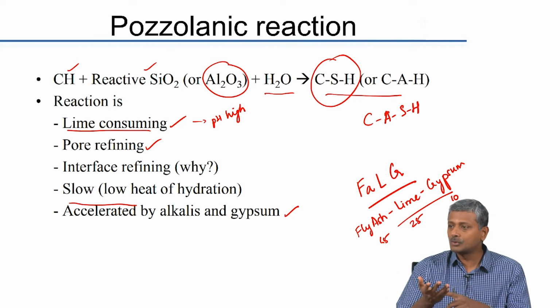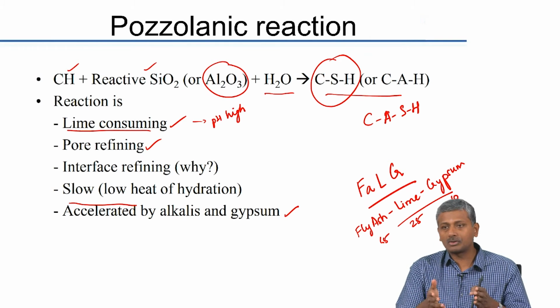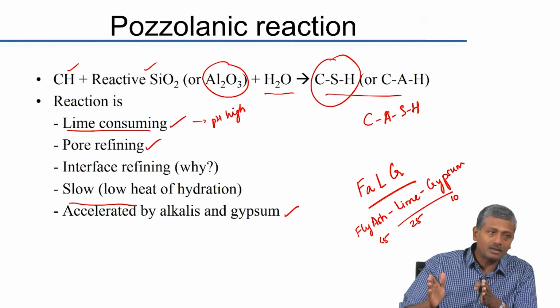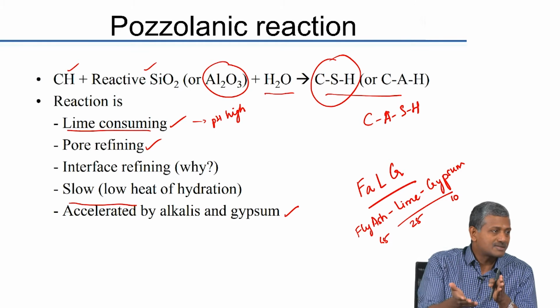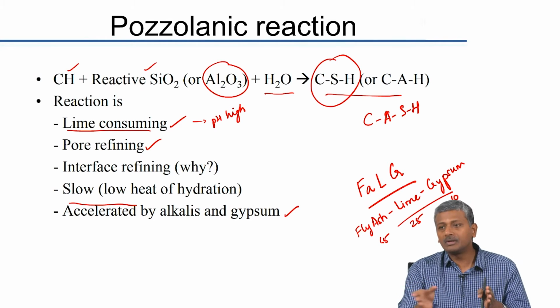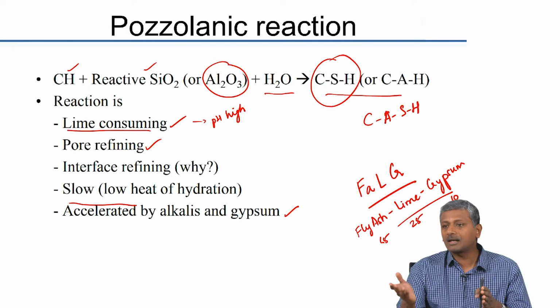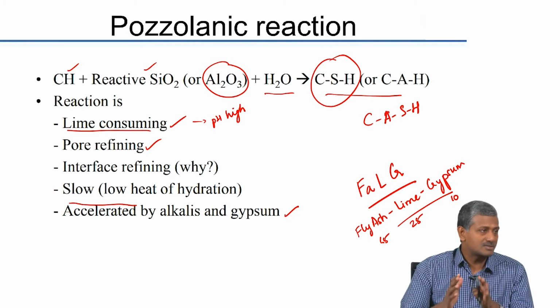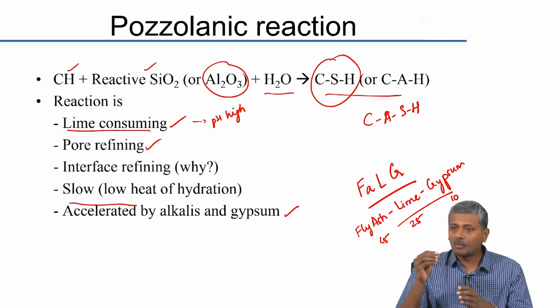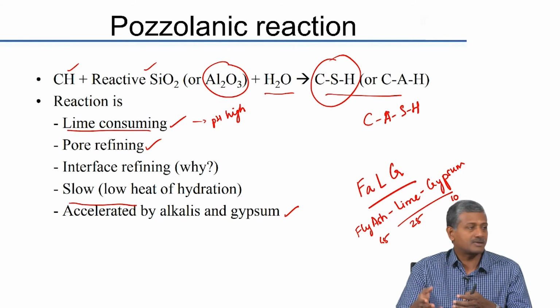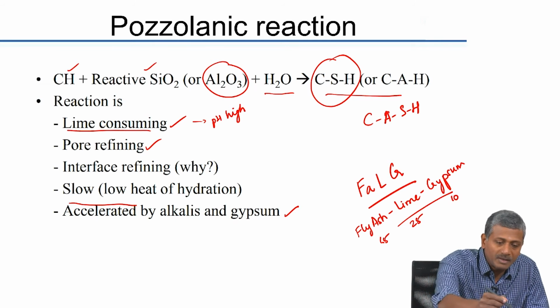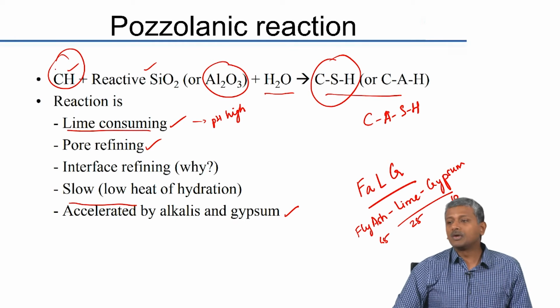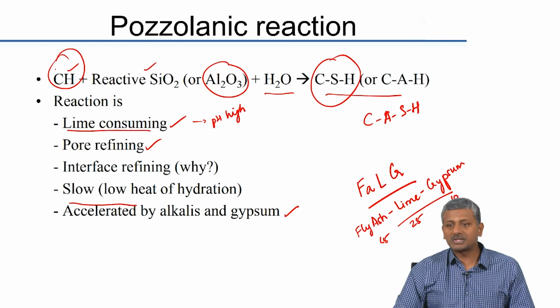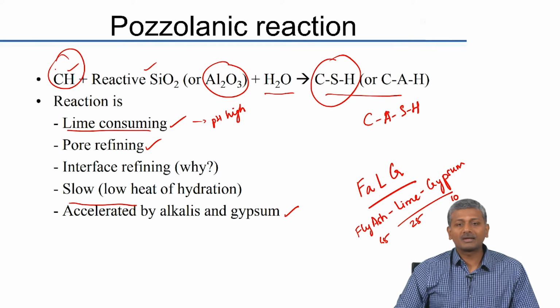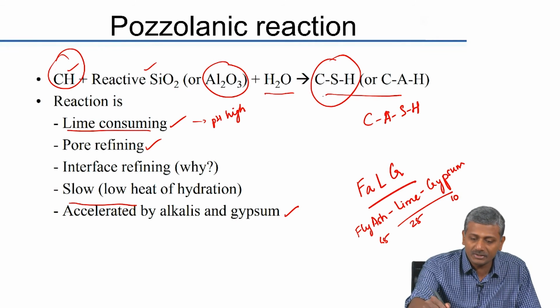Now, the real impact of CO2 attack on concrete or carbonation on concrete is that it converts your alkaline system into a less alkaline system, not acidic yet, but it lowers the pH to about 8 to 9. At that level, your steel becomes unstable and starts to corrode. So, that is the primary effect of carbonation. The effect on the cement paste is actually more positive, because formation of calcium carbonate densifies the structure and strengthens it. Now, in mineral admixture based systems, you are removing your lime, you are removing this buffer which was otherwise there to contend with the incoming agents, okay, and then you are producing CSH.